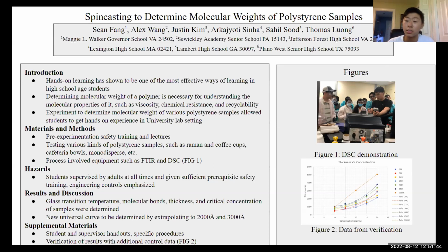So looking at the results of our initial project, glass transition temperature, molecular bonding, thickness, and critical concentration of the samples of polystyrene were determined. And a new universal curve is currently being determined, which will be discussed in the next presentation about extrapolating to the 2000 and 3000 angstrom thickness.